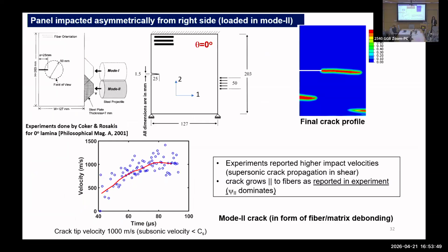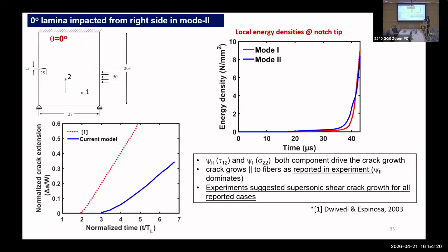Okay, so we continue to do more experimental validation. So this is another experiment that we looked into. It was done by a group at Caltech, led by Professor Rosakis. They have a laminate in one particular fiber orientation, and they hit it with a steel impactor on one side and monitor the crack propagation under symmetrically impacted and asymmetrically impacted specimens. And we saw that qualitatively the behavior matches, even though currently our model does not show a very good prediction.